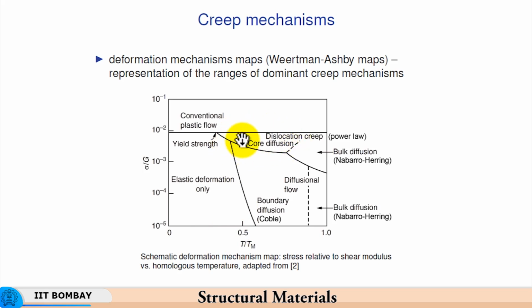So, this is the situation where, let us say you have a boiler which is very heavily loaded, and the stresses are a little close to yield point. You see that there is a yield strength over here, and the stress which is being experienced is a little lower than the yield strength, but very close to it. So, you have what is called dislocation creep taking place, and as the temperature keeps on rising up to even 0.75 or so, you need much greater stress to cause dislocation creep.